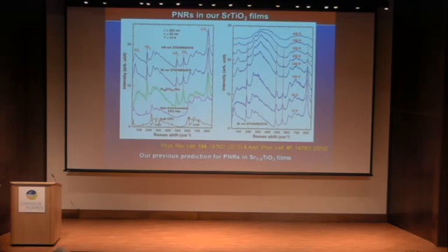However, you see a clear indication of the polar nanoregions in the system. When you increase the temperature from 10 Kelvin, you still see some signal up to room temperature, and this is some kind of indirect evidence of the nanopolar regions.